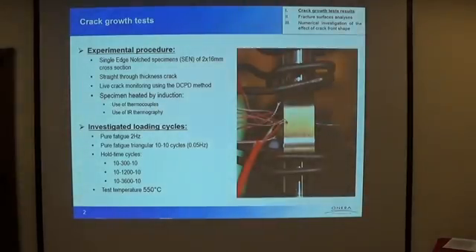Alright, let's have a word about our experimental procedure. We performed crack propagation tests using single-edge notch specimens. We have a straight through-thickness starter notch machined by electro-discharge machining on the right. And we monitor the crack lengths using the direct current potential drop data, the well-known DCPD technique. We investigated different cycles: one which is our reference cycle, a pure fatigue loading cycle at 2 Hz of frequency, and triangular 10-10 cycles with 10 second loading, 10 second unloading, and finally hold-time cycles with 10 second loading, 10 second unloading, and different hold times of 5 minutes, 20 minutes, or whatever. And all of those at 550 degrees.